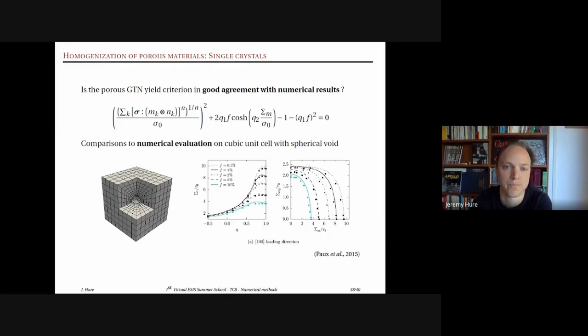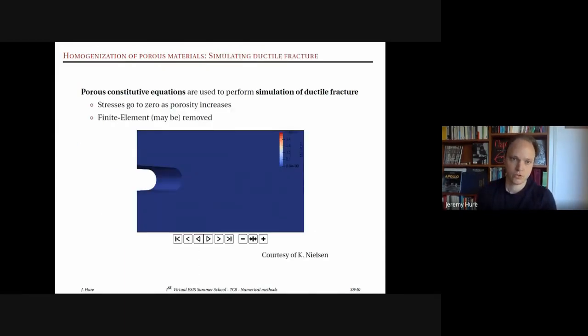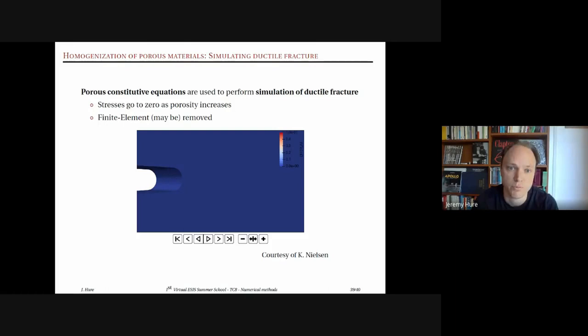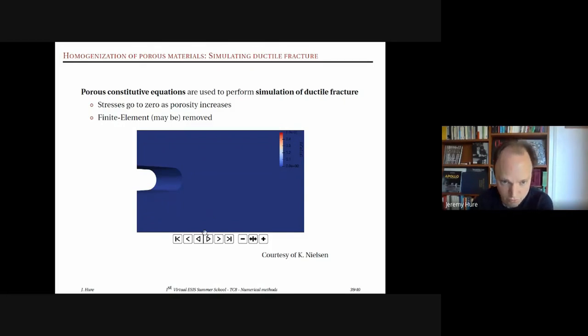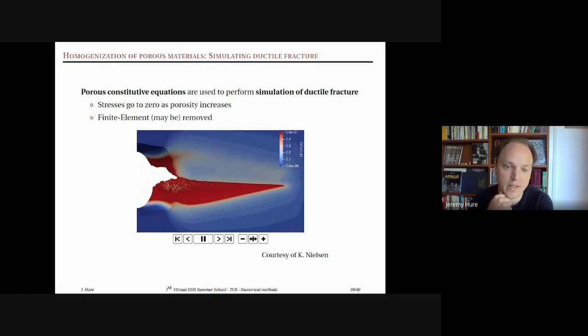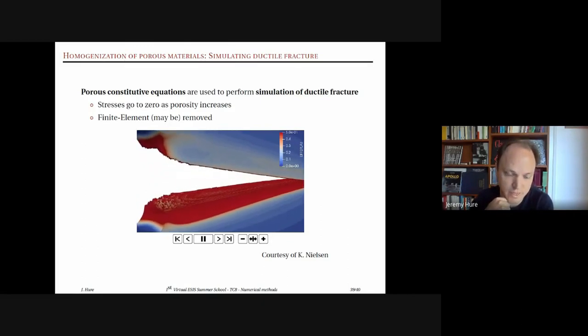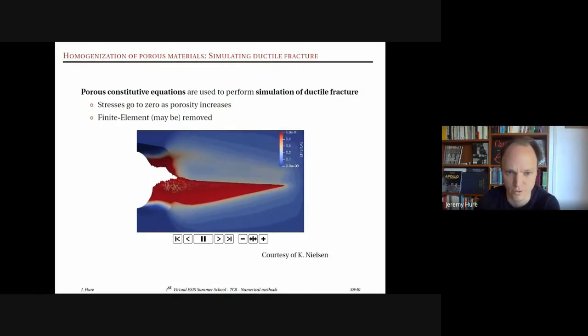Finally, these porous constitutive equations can be used to simulate ductile fracture in finite element analysis. As porosity increases, stresses go to zero, and very soft finite elements can be removed since they no longer contribute to mechanical equilibrium. A simulation of a notched specimen under tension shows plasticity developing first, followed by fracture as porosity increases in the finite elements.